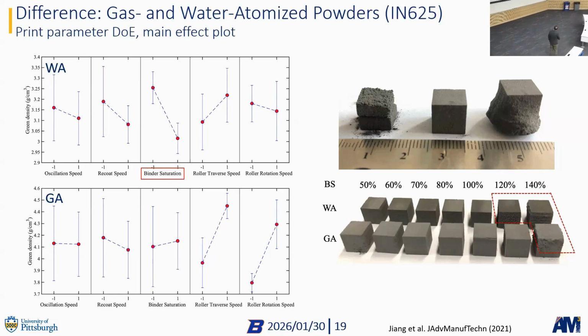And what we can see here is actually really nice structures in the middle, so around 80 to 100% binder saturation. Then we have binder bleeding, and at the bottom, the lowest binder saturation resulted in delamination. So the parts were just too chalk-like, right? They were not even chalk-like anymore, right? They just delaminated.